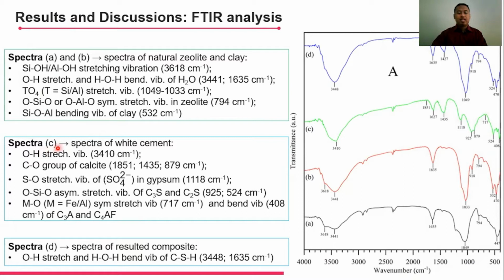Then spectra C refers to spectra of white cement. From this spectra, we get information about hydroxy stretching vibration, carbonyl group of calcite, SO stretching vibration of sulfate groups in gypsum, OSiO asymmetrical stretching vibration of tricalcium silicate and dicalcium silicate, and the last is MO, with M being iron or aluminium, symmetrical stretching vibration and bending vibration of tricalcium aluminate and tetracalcium aluminoferrite.